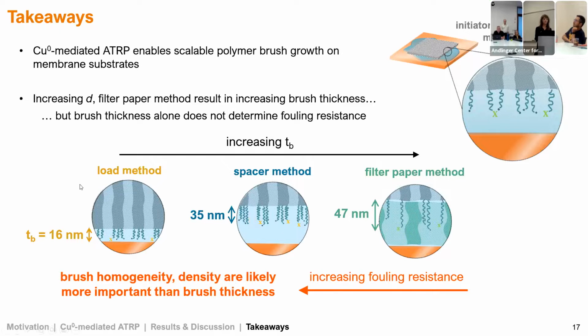And so that is something we considered, especially with the spacer method, where we saw a wetting of the pores. One possibility is that we were getting interpore brush growth there. The interesting thing is that the way we functionalize our membrane substrates with initiator sites is plasma treatment, and we don't expect any initiator sites on the pore walls, just because the mean free path is too big to get in there during plasma treatment.